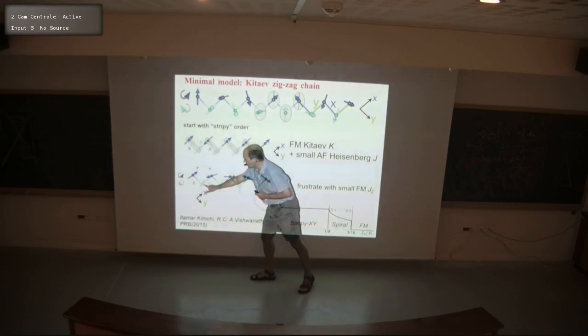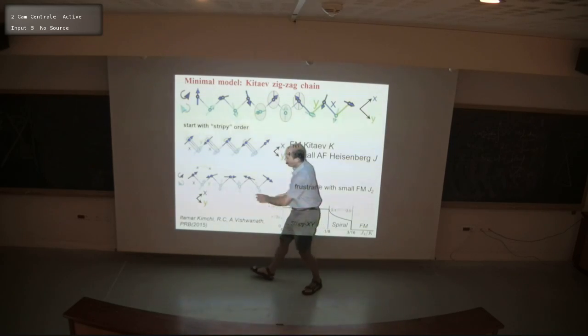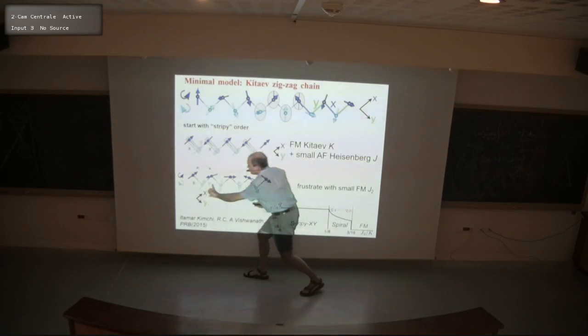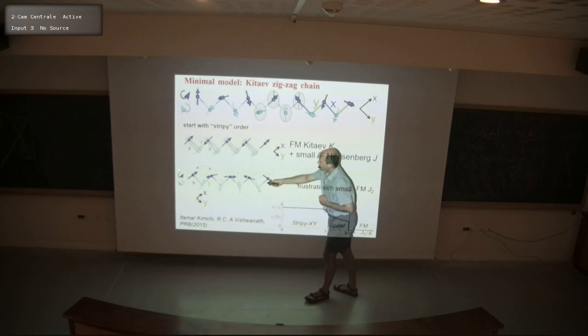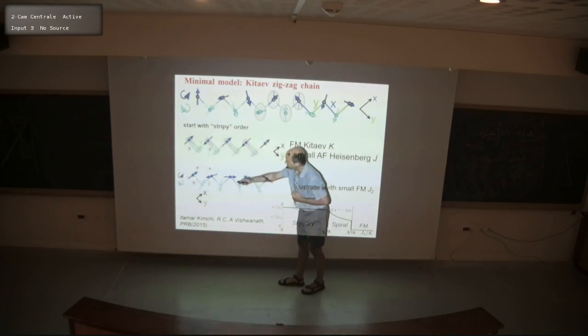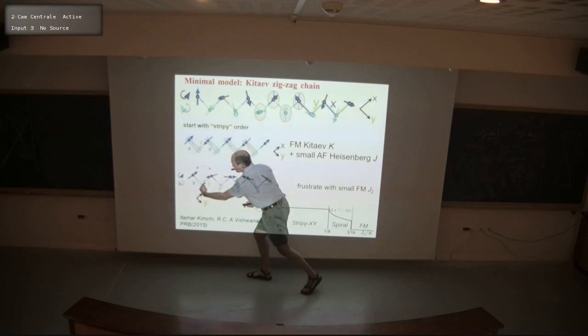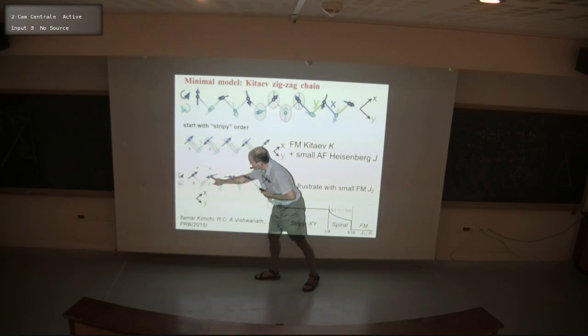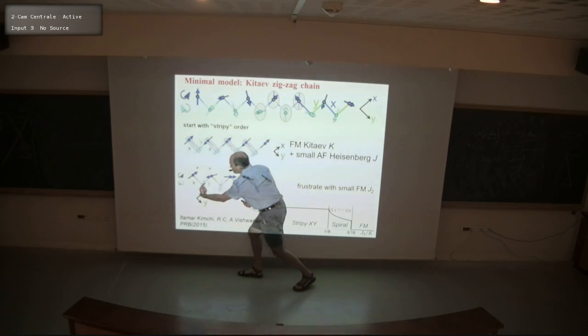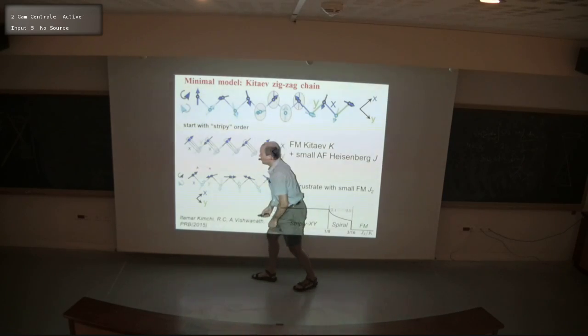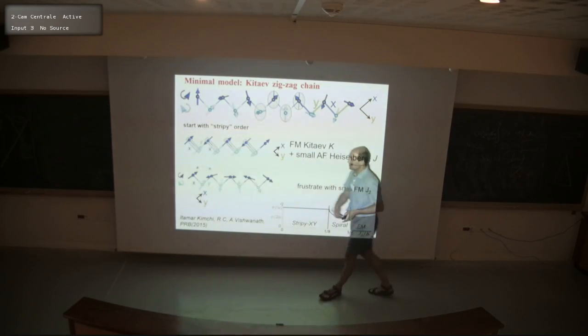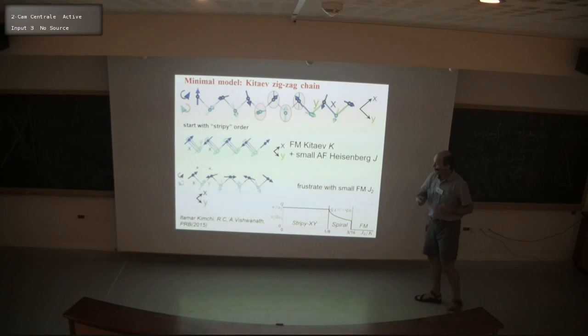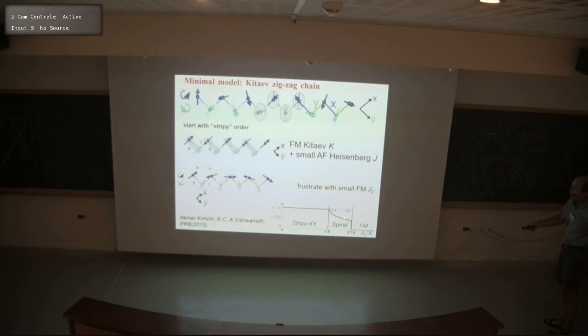So let's look at this spin up here. This will also rotate, and it has two choices. It can go to the left or it can go to the right. And in terms of the Ising interaction for this bond, it doesn't really make a difference if it goes to the left or right. But in terms of the interaction with this spin up here, which has already chosen to go that way, then if the spin goes in the opposite direction, then it will gain energy from the Kitaev interaction this way. And so these two spins counter-rotate. And when this is propagated along the same chain, this leads to this type of co-rotating spiral with opposite wave vectors on the two sublattices.